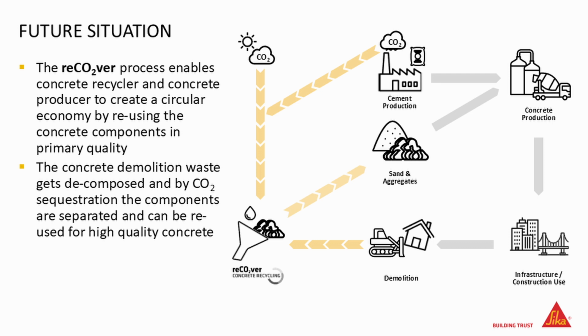So, the other story is that we also can introduce CO2 into the process. And this is the second aspect, the CO2 in recover. Because when you grind, or when you put the friction and you have this powder, this can be very fast and easily carbonated. So the CO2 reacts really fast with this powder, so we can bind CO2 in this process as well. So we can have the circularity aspects by cleaning the aggregates from the cementitious parts, and we can have the CO2 sequestration part, which is much, much faster by combining it with grinding.